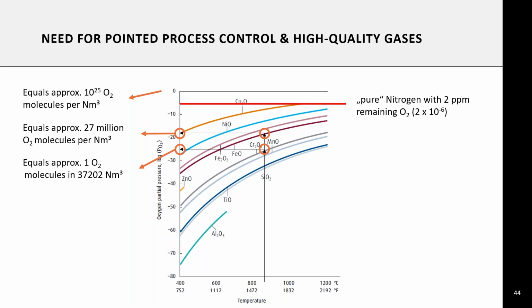And to avoid oxidation of iron, for example, during carburizing, say at 880 degrees C, an oxygen partial pressure is required which equals about 27 million oxygen molecules per cubic meter. To avoid oxidation of chromium at 880 degrees C, an oxygen partial pressure is required which equals about 1 oxygen molecule per 37,202 cubic meters. To enable good and reliable heat treatment results, both the gas quality as well as an understanding of the heat treatment atmosphere are key factors.